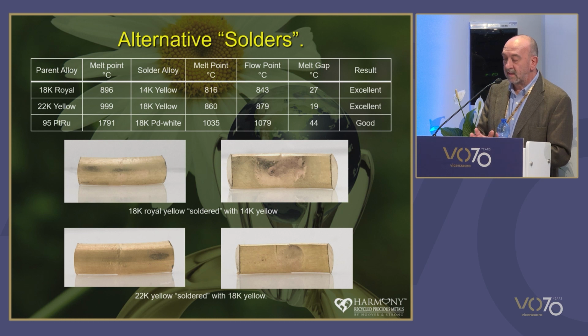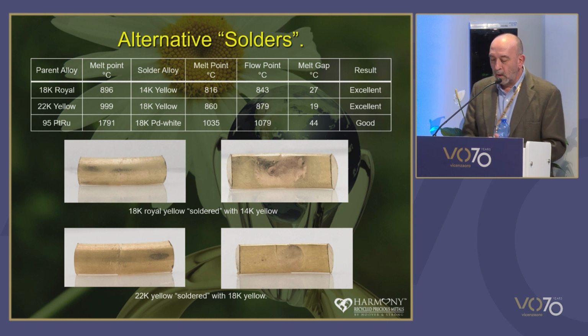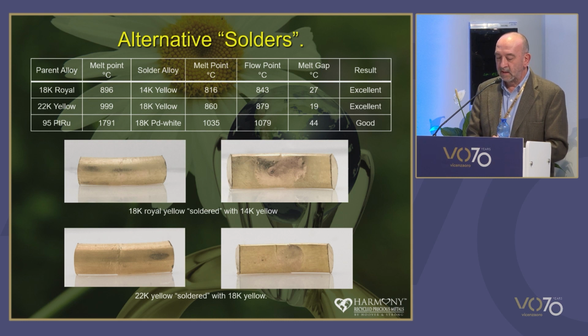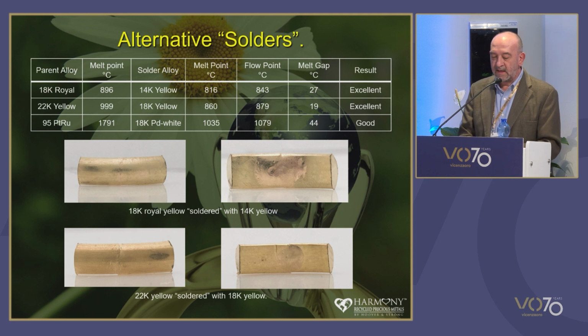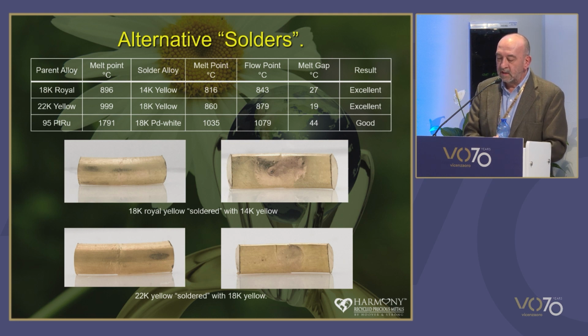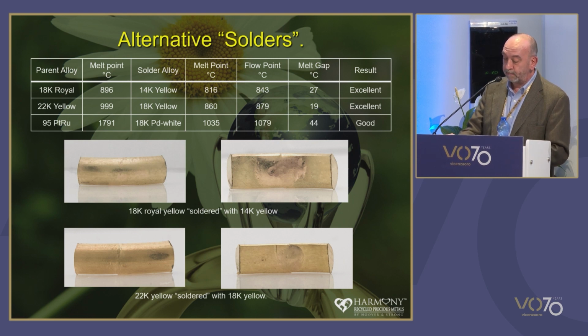Furnace soldering is a standardized process and well suited to volume production. And once the furnace parameters and the solder quantities have been determined and dialed in, this method does give consistent results time after time. And the main thing we take away from this is that probably the most important variable in any soldering operation is the joint quality. Even with the best solders, with poor joint geometry, the joint is going to be poor.